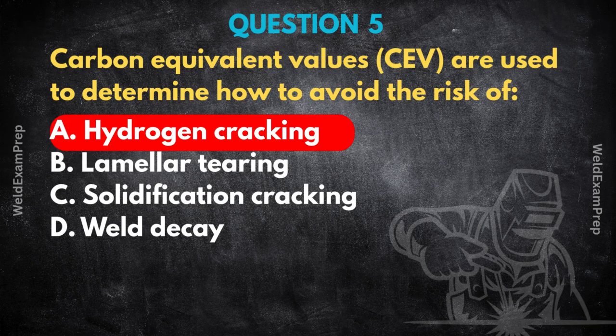What does it calculate? The carbon equivalent value, CEV, is basically a formula. It takes the percentages of various alloying elements in the steel. Carbon is the main one, of course, but it also includes manganese, chromium, molybdenum, vanadium, nickel, sometimes copper. The whole gang. Pretty much the key players that affect hardenability. And it combines their effects into a single number that represents the steel's overall tendency to harden. Okay, so it quantifies hardenability. Exactly. A higher CEV means higher hardenability, which means, going back to our earlier discussion, the steel is more prone to forming those hard, brittle microstructures like martensite in the HAZ when it cools quickly after welding.